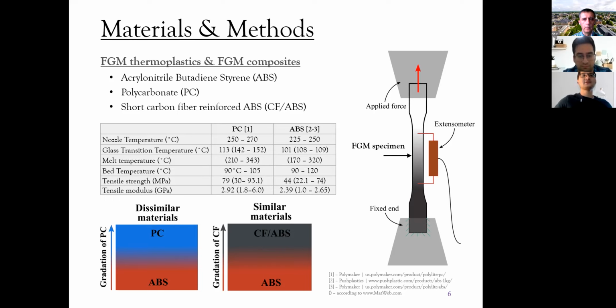And for nozzle temperature, we have a balanced temperature range. So we decided to print our samples at 250 degrees Celsius, so that we can mix polycarbonate and ABS in one melting chamber. And we use the tensile testing method to characterize the interfaces of these materials.